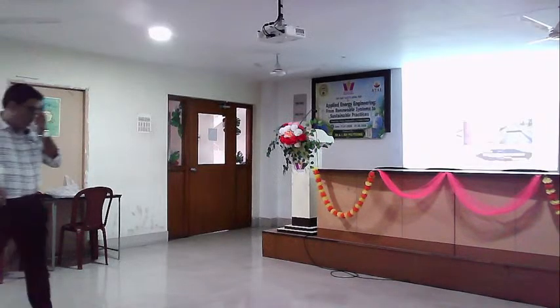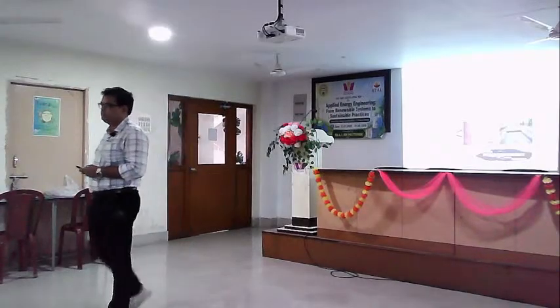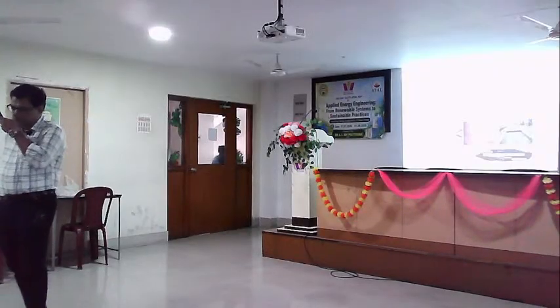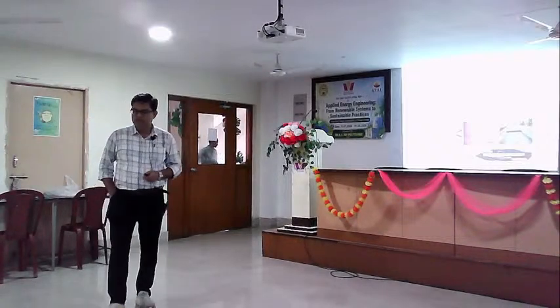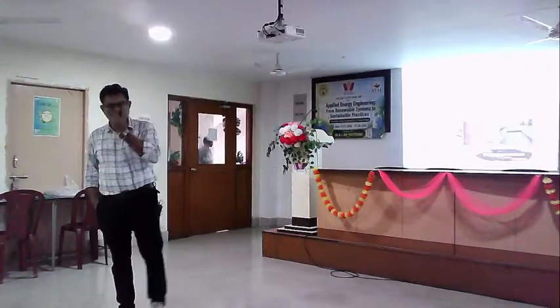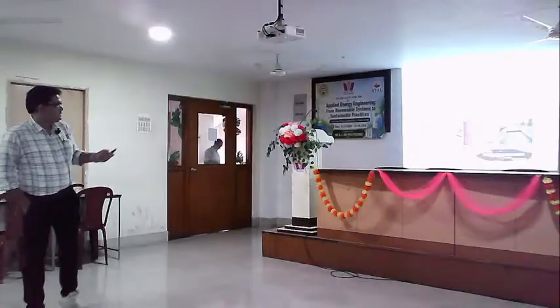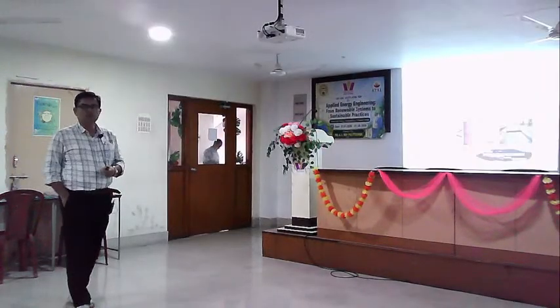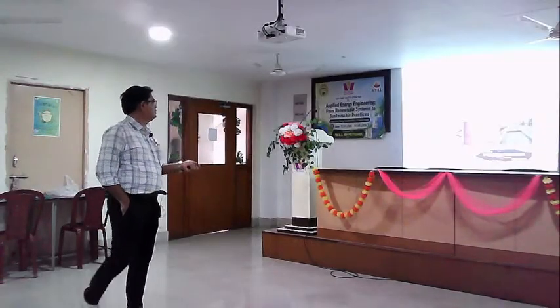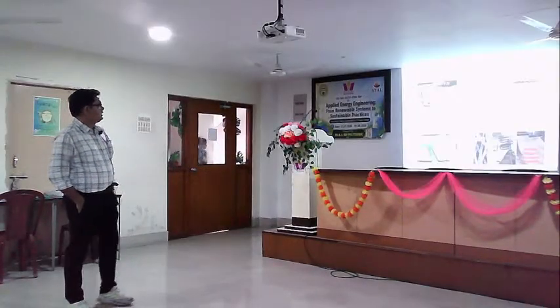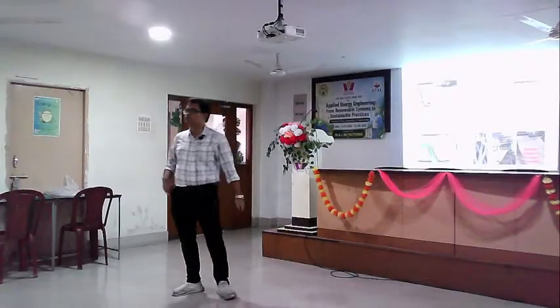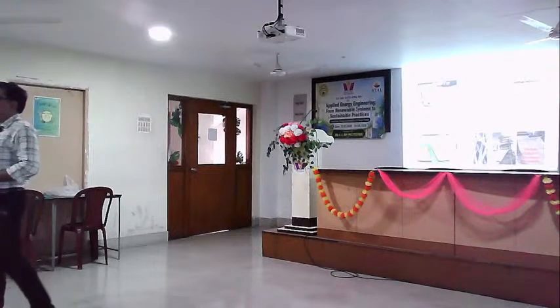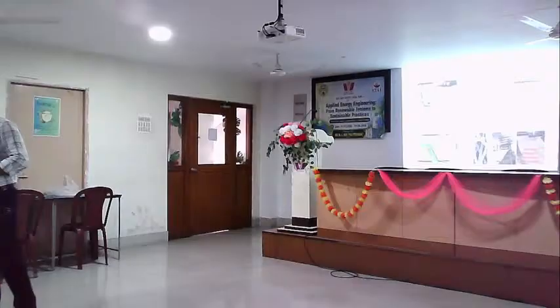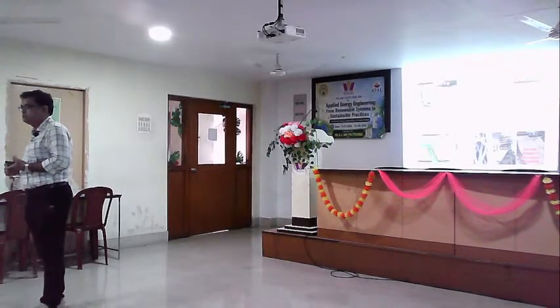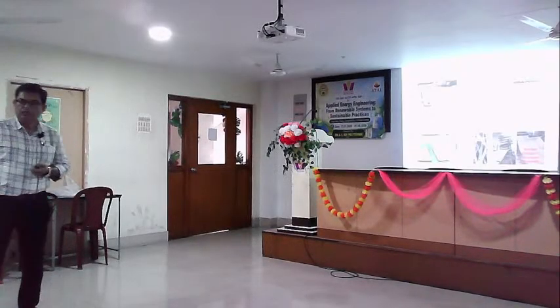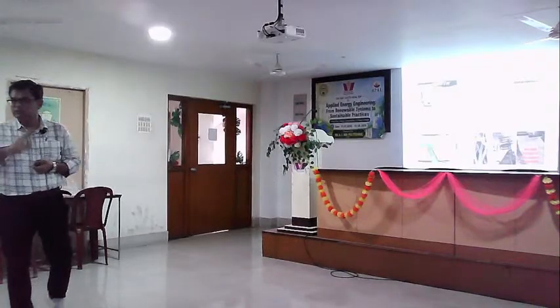So what we did, we used some nano composite solution that we have developed at NIT Durgapur. With me we have professors from the Chemical Engineering Department, Professor Mandal and Dr. Rajiv Ghosh. So this nano composite solution basically gives the strength, and it is generally made of one non-toxic, water soluble polymer that we have used as a binder material, as well as nano material, mainly silicon dioxide for this particular project.